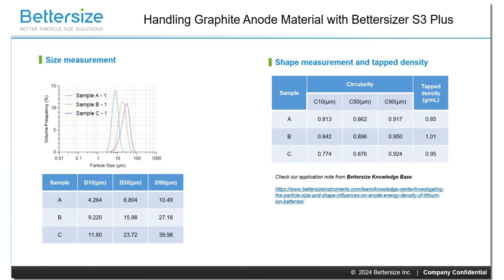In a Bettersize application lab, 3 samples were measured. They are of different sizes, a bit similar shape, and different tap densities. As we can tell from the data, sample B is not of the largest size or smallest, but it has the largest sphericity value. This means the particle of sample B is the roundest among 3 samples, and a more important thing is the tap density of sample B is the largest. That indicates sample B will help maximize the energy density of the battery. So, despite the particle size comparison, sample B would be the most welcomed one among these graphite samples. More details and insights are written in our application note, including how the sample is being measured and why the tap density should be maximized. Please search over the Bettersize knowledge base for this application note.